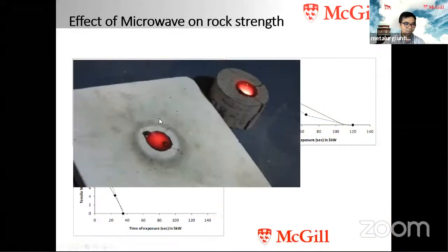And in some cases, the rock melts because it heats too much. This is actually what we don't want to do, to heat up the rocks and melt the rocks. Because for some of our samples, we got the kimberlite sample from diamond mines, and the company basically doesn't want to burn the diamond. So what we want to do is really reduce the strength of the rock and then attack it with the mechanical cutter, and some of the micro cracks are still there in the rocks, which further will help with the crushing and grinding of the rock, so that the energy from mine to mill can be reduced significantly.